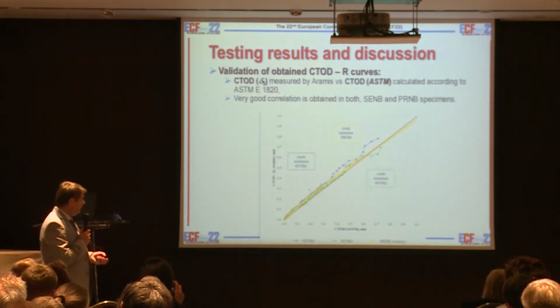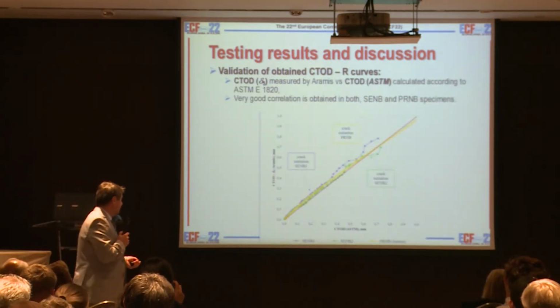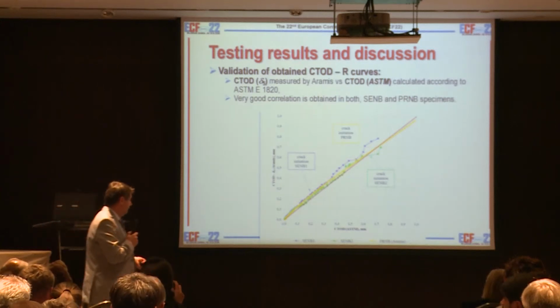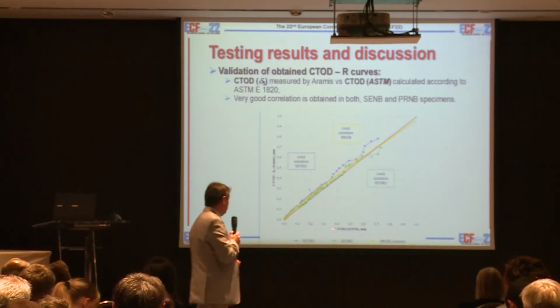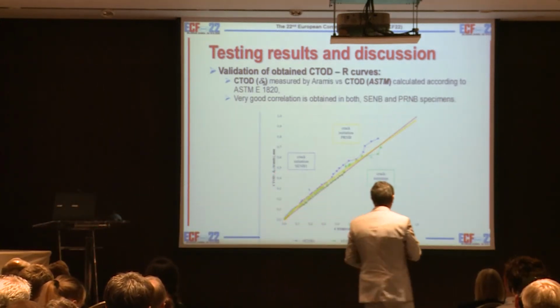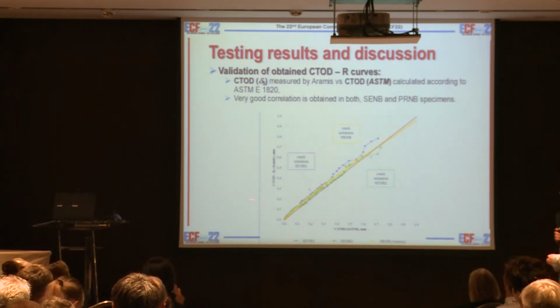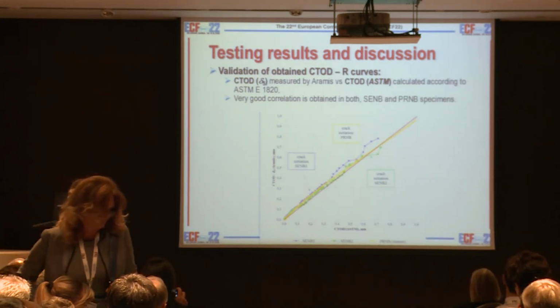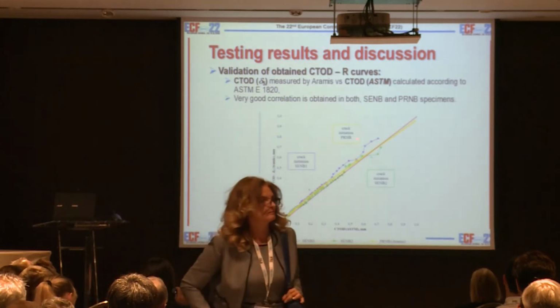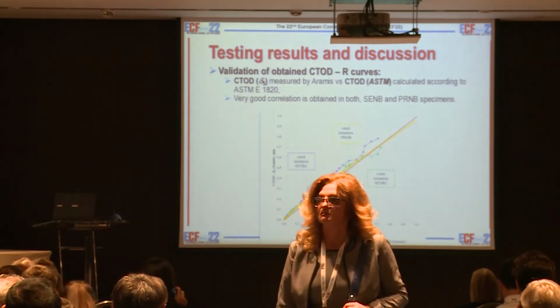So we have the same material. Here you can see the correlation between the delta 5 and the CTOD, which you measured from the 3-point bending specimen, but also what we do with the pipe ring specimen. So this is one line here.